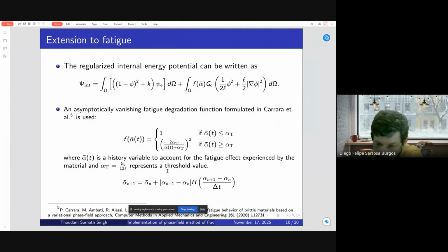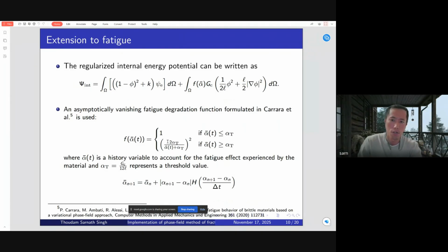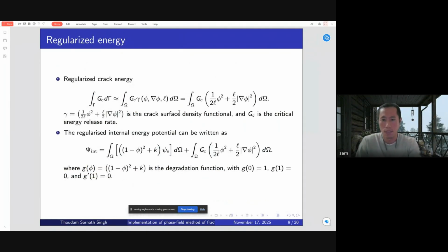Go ahead. Okay. So if we want to incorporate more physics into the system, here in this expression we have this critical energy release rate. Imagine if we have a cyclic loading, or a fatigue kind of loading. With time, it would degrade the fracture toughness of the material. So in that condition, we have to degrade the GC term, the critical energy release rate. So when we apply cyclic loading, this term would degrade. So how do we capture that?